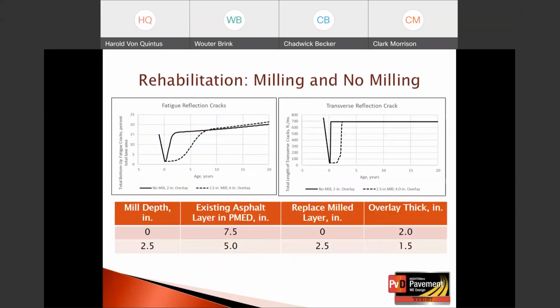So now, milling and no milling. We have 2 examples that I've shown here from an example. We have a mill depth of 0 and then a mill depth of 2.5 inches. We have an existing pavement layer from cores, the first one would be 7.5 inches. That's a mill depth of 0. We're going to mill 0, and then we're going to simply place an overlay of 2 inches.